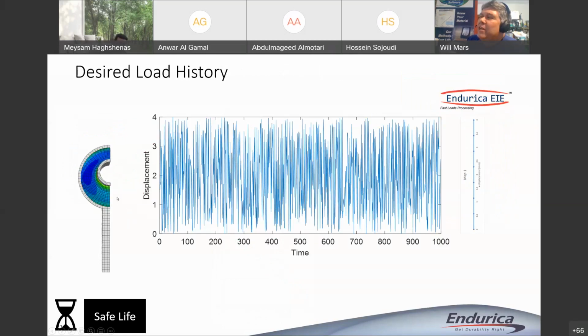And if, for example, we wanted to model a uniaxial load, right? Since this is just a link, this link gets loaded uniaxially. So we can just look at the displacement history, maybe from a road load recording. Now, since these are road loads, we don't want to just feed this road load directly into the finite element model, because that would just take way too long. What we're going to do instead is compute a map, right? So we're basically going to take the part, we're going to load it from 0 to 4 millimeters of displacement. And in this case, we're going to do that in about 8 increments. Those 8 increments of loading create a one-dimensional map of the relationship between stress strain fields in the part and force displacement input to the part.